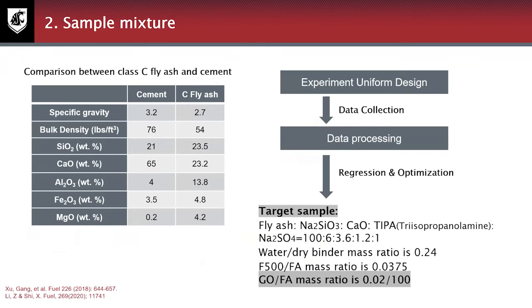The left table provides some physical properties and the chemical composition of Portland cement and Class C fly ash. Based on the difference in chemical composition, we did some adjustment and introduced some chemical activators to prepare geopolymer. We employed the uniform design and prepared 36 samples. Then we tested the strength and collected data, did regression analysis and optimized the regression model. Then we can obtain this target sample, which features the highest strength performance. The proportion is listed here. Based on our previous research, we fixed the mass ratio of GO to fly ash at 0.02%.